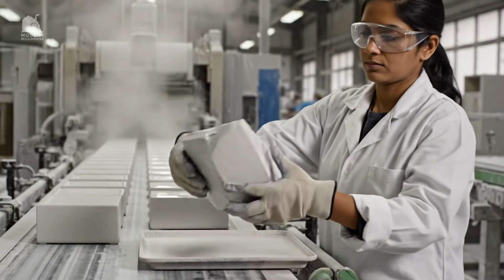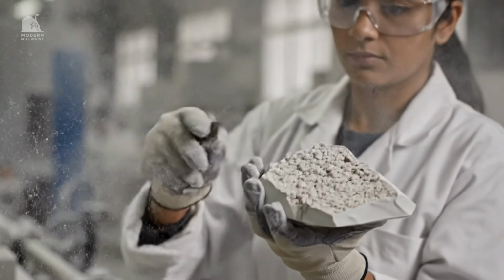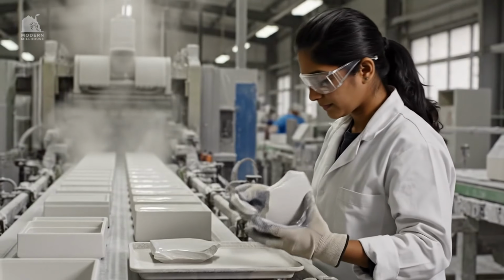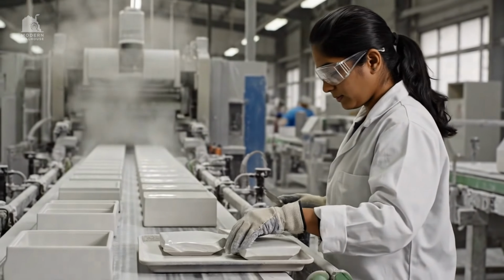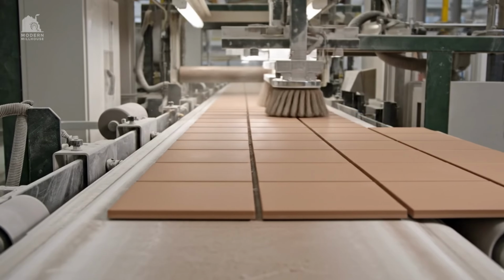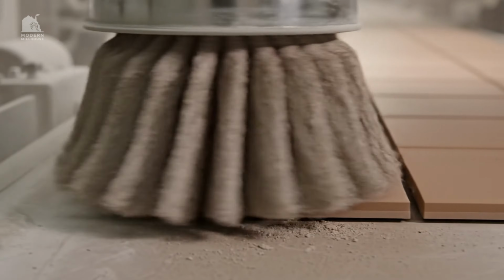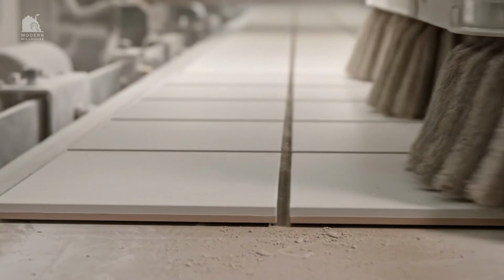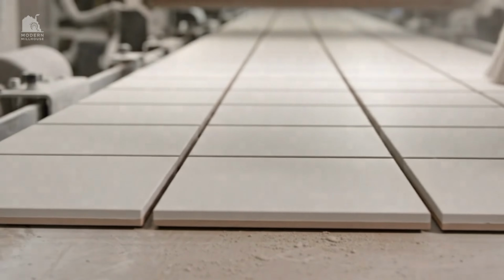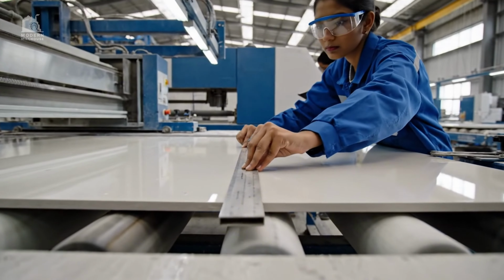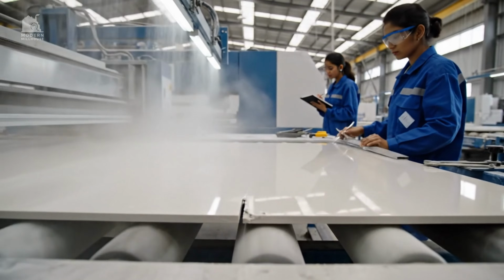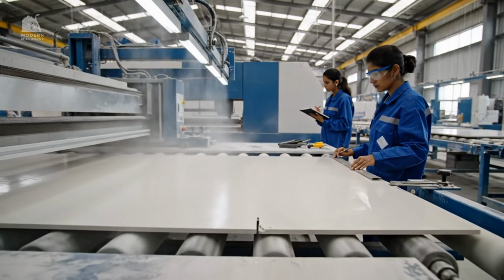Dryers aim for a final moisture that is low enough for safe firing, but not so low that surfaces become dusty. If the tile surface is dusty, glaze adhesion becomes unreliable and crawling risk increases. Some lines use light misting or controlled humidity at the end of drying to stabilize surfaces before glazing.